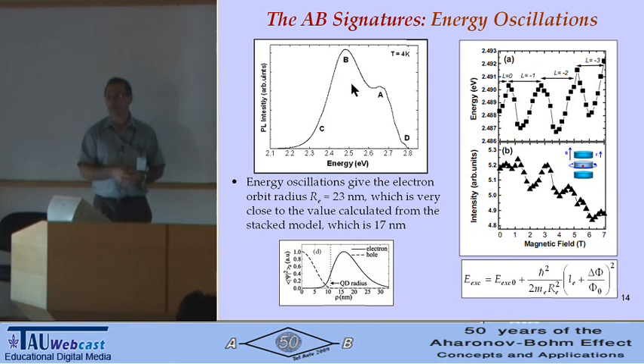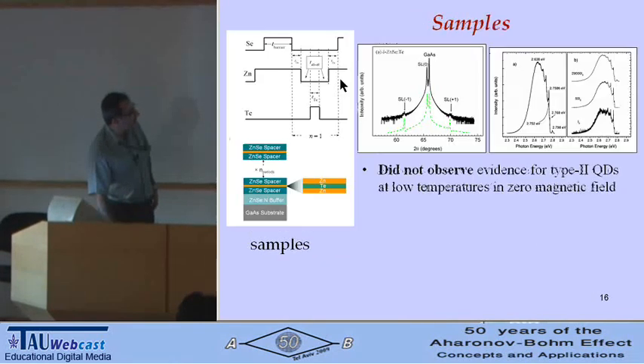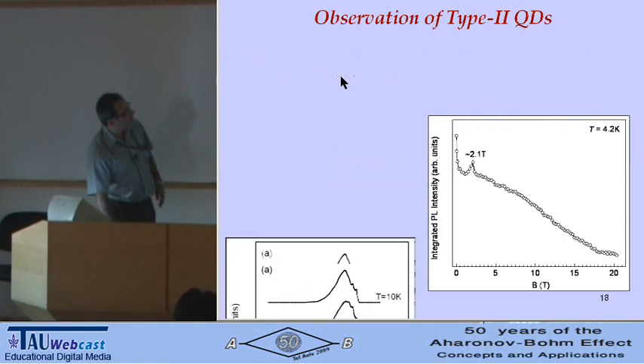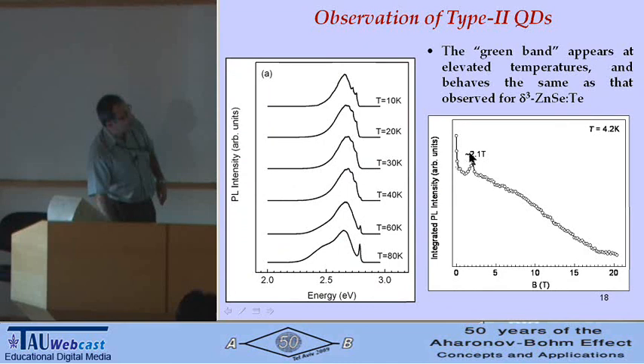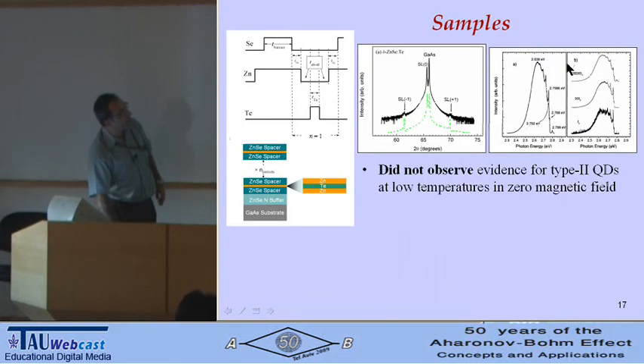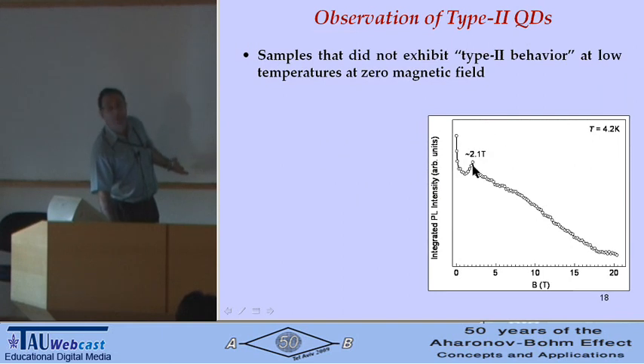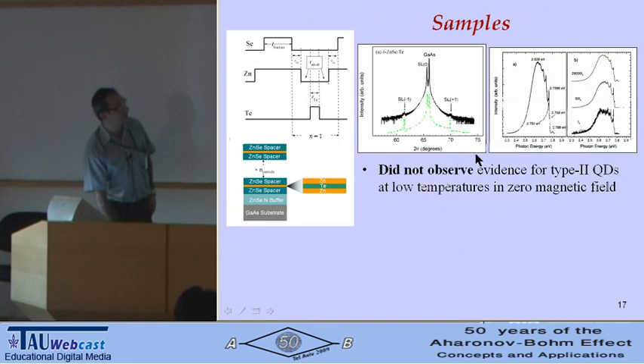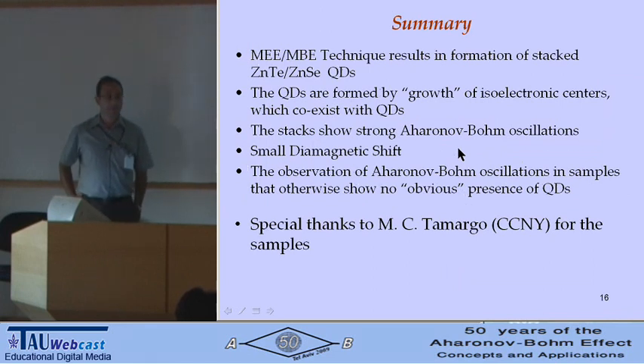And as I said, I'm out of time, but we saw oscillation of peaks which have nothing to do with the quantum dots. We don't understand it. I can quickly show you that we see oscillation like this on peaks which have nothing to do with quantum dots. If you do the basic analysis of the photoluminescence, you would assume there are no quantum dots there. But if you do magneto-optical measurements, you see Aharonov-Bohm oscillations. That's another one of the puzzles we don't understand yet. So that's the only thing I can answer you. Thank you.